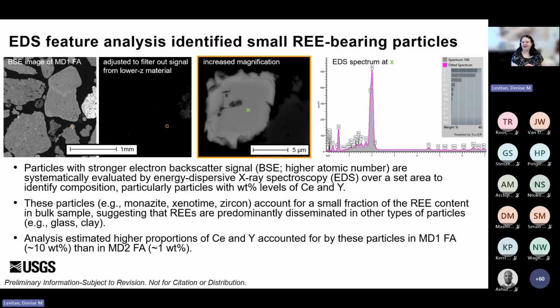So we can scan an area looking at these bright spots, and then we can measure these particles and get an idea of the total area over a specific small area of our thin section sample. And then we can compare that area and the composition of those particles to the overall composition and area that we have from the bulk samples.